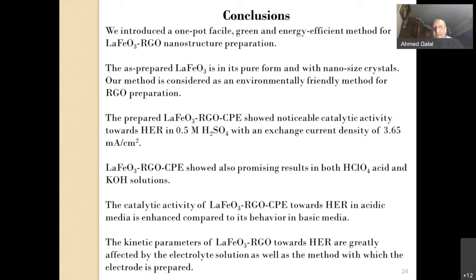The as prepared lanthanum iron oxide was confirmed to be in the nano size, and it was in a pure form. The prepared composite showed a noticeable catalytic activity for the hydrogen evolution reaction with an exchange current density of 3.65 milliampere per centimeter square. We have different catalysts prepared currently for the same purpose, and we are also testing the effect of adding some ions and organic components to the medium using these particular catalysts.